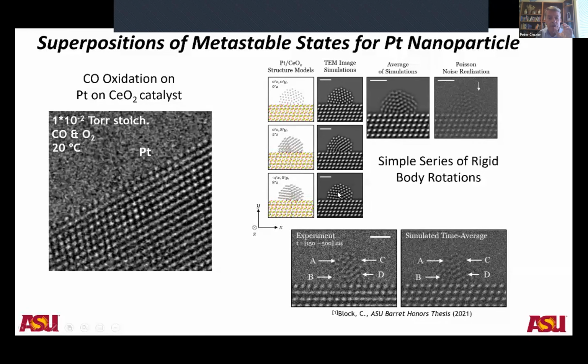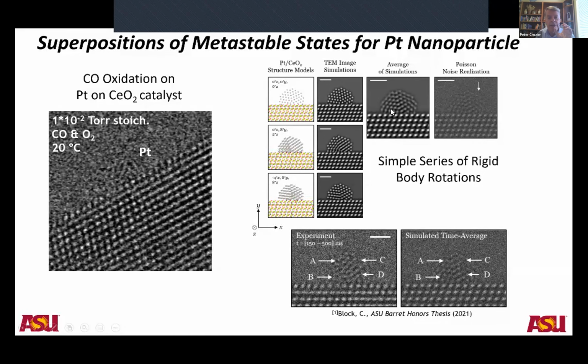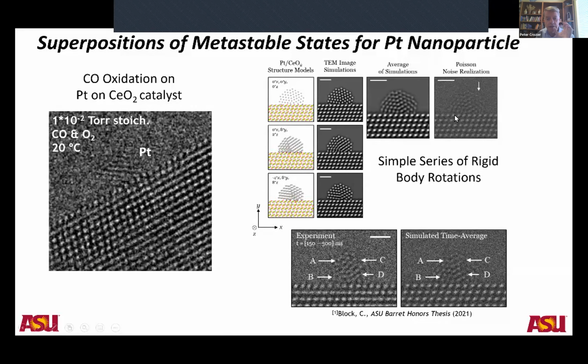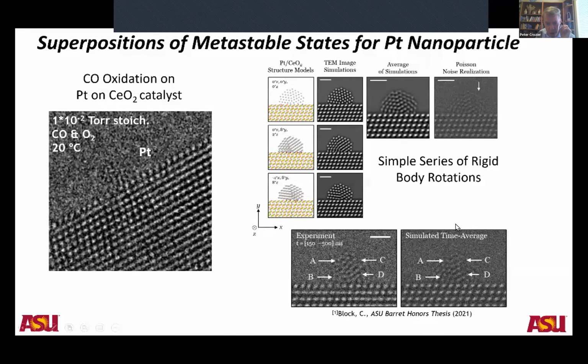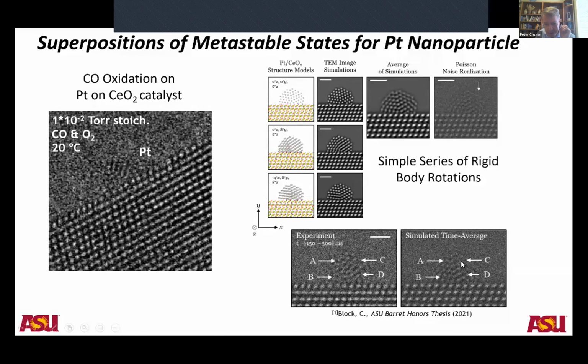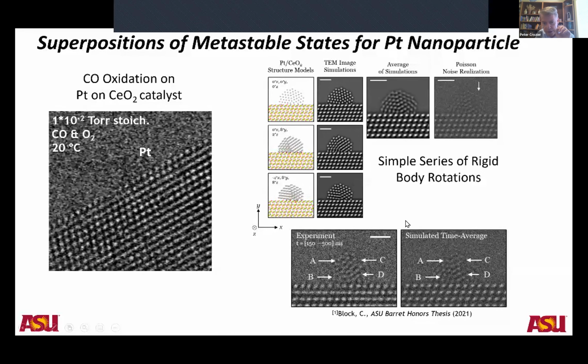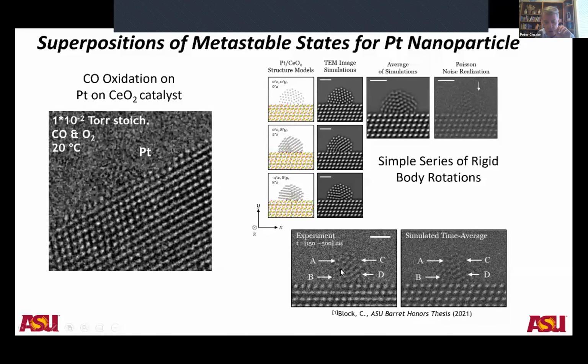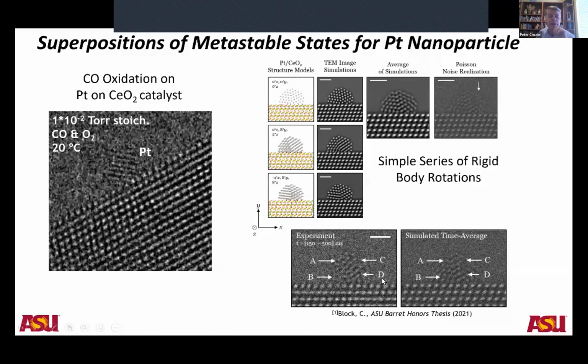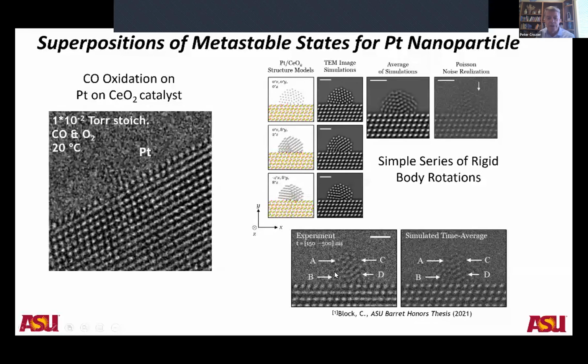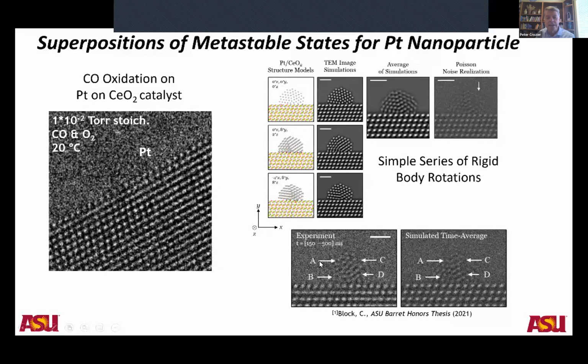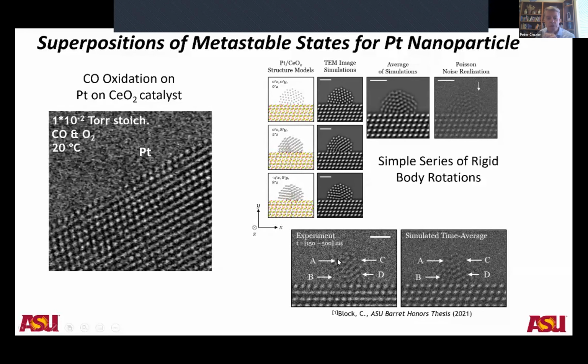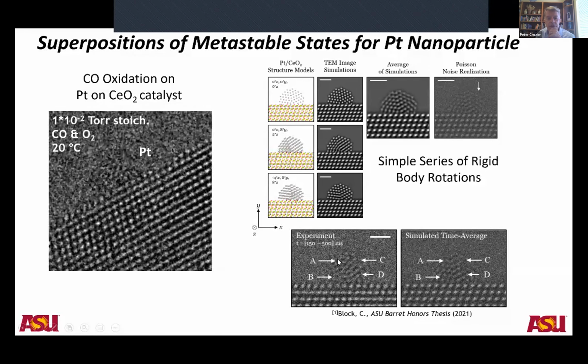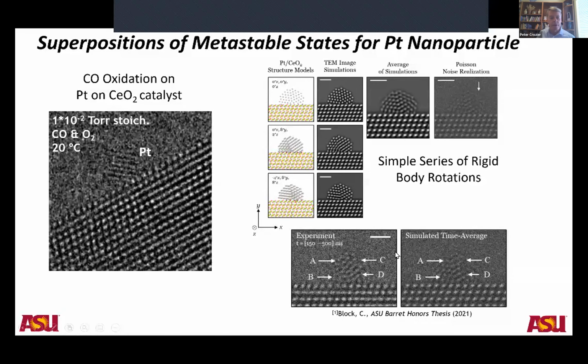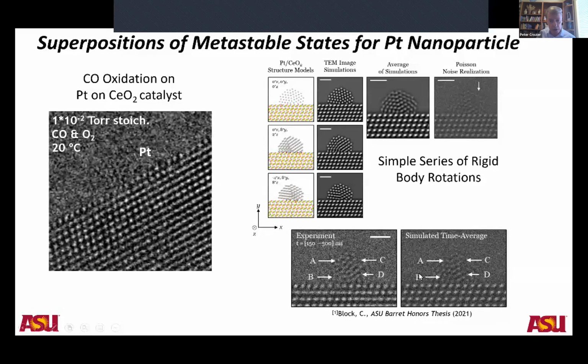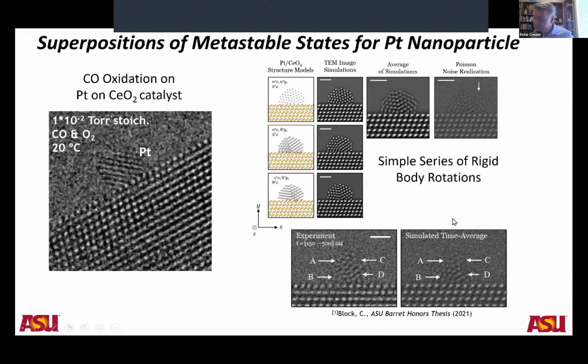She calculated the images for different rigid body rotations and then superimposed them together and added some noise. And here's what she got. The right hand is Claire's simulation of a superposition of different metastable states. And the left hand is one of the frames from this crazy movie over here. Even though they don't match exactly, it certainly tells us that this idea of observing superpositions of different configurations is probably the correct interpretation. And if she had worked a little bit harder, she might have been able to get a better fit.